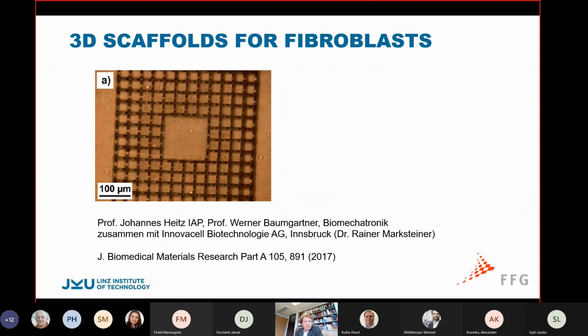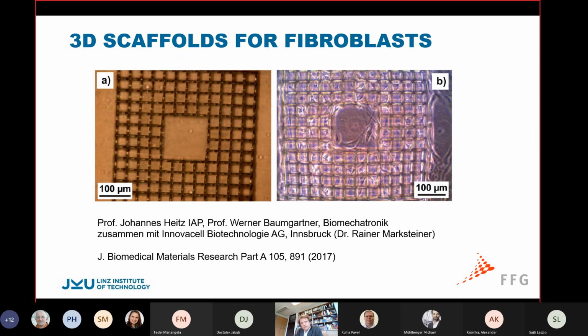And a couple of examples from our institutes, most of them by the group of Johannes Heitz. What they did is, for instance, they made a 2.5-dimensional grating, and then they incubated this grating with fibroblasts, and you see that the fibroblasts tend to occupy these containers. So you can make a scaffold for cells, and later on in that project they also showed that these fibroblasts can be convinced to calcify, to make a sort of a precursor of a bone.